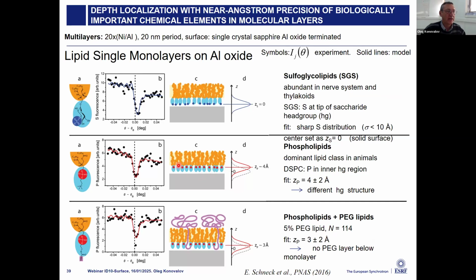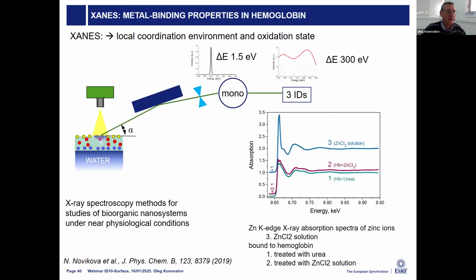For example, this one is a phospholipid DSPC monolayer. In one case, without the PEG, and another one with PEG lipids, and we can see whether it is inserting in between or not. And from these measurements, we can see that it is mostly organized on the top, but not going in between the substrate, because there is no change in the fluorescence signal.